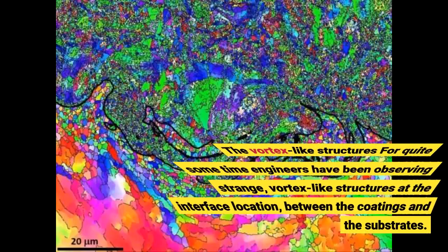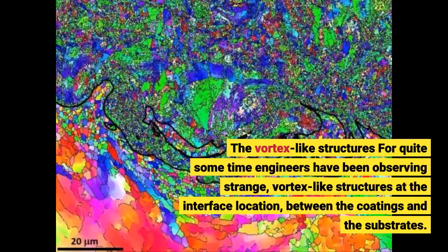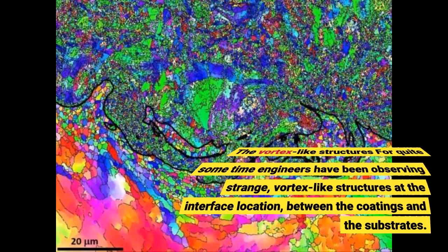The vortex-like structures. For quite some time engineers have been observing strange, vortex-like structures at the interface location between the coatings and the substrates. They are much smaller than the particles, which presented a puzzle. What are they and how do they form? What's more, these structures don't always appear and, when they do, they show up in a rather random fashion.